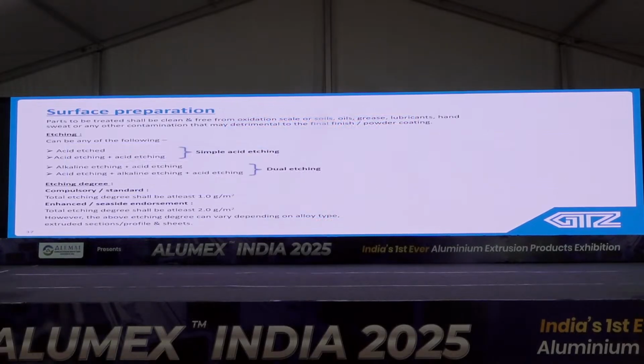So, surface preparation for pre-treatment, etching: one is simple etching, just acid etching, then double tank acid etching plus acid etching. Then there is dual etching: alkaline etching, acid etching, alkaline etching followed by acid etching. So these are the different types of etching conditions, and etching degree is as per code specification. For general purpose, 1 gram per meter square etching is required, and for the seaside endorsement, it can be 2 gram per meter square.